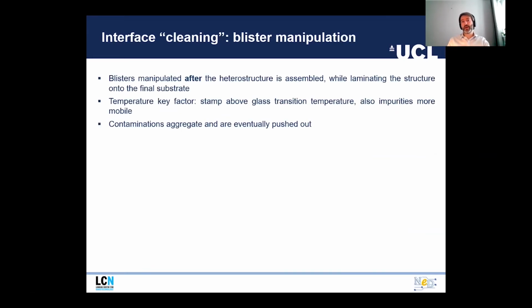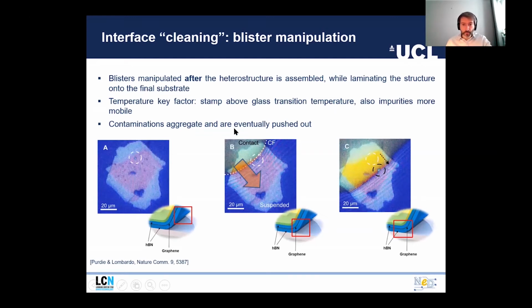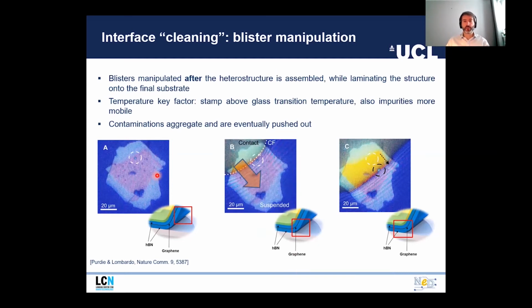So we developed a method to manipulate the blisters. Unlike other methods that were available before, we decided not to care too much about the formation of the blisters when we assemble the heterostructure, and rather focus on how we can eliminate the blisters once the full heterostructure is formed. We developed this method which combines two factors: temperature and a mechanical push. The method works as follows. Let me open the laser pointer. This is an example of a heterostructure consisting of graphene encapsulated between two layers of hBN.